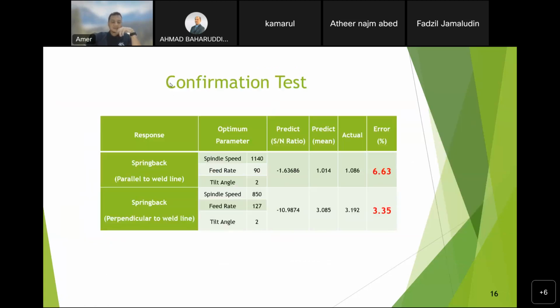After the test and getting the result, I did the confirmation test. The confirmation test was used to compare the experiment result to the predicted outcome. The table shows the margin of error between predicted and experimental results for the springback values, where the difference is only 6.63% for parallel and 3.35% for perpendicular to weld lines. This means all the experiment data and results are trusted and reliable.